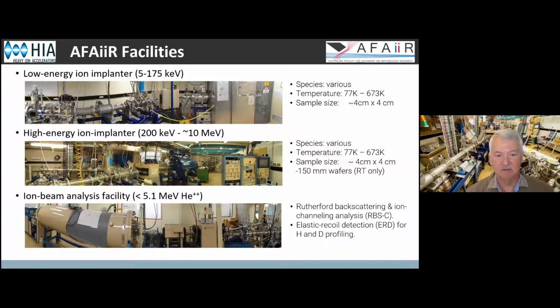This is a tandem accelerator, and I won't go into the details of how the tandem accelerator works, but basically it allows us to get to relatively high energies based on the charge state of the ion. The higher the charge state of the ion, the higher the accelerated velocity for a given potential. So energy range of 200 keV to 10 MeV. Again, similar temperature capability from liquid nitrogen temperatures up to around 450 centigrade. We do have a second beamline on this facility for 6-inch wafer implants, so 150 millimeter capability. That requires some special care to avoid ion neutralization effects in the beamline, and we have that capability with an electrostatic deflector towards the end of the end station to allow us to implant large area wafers without contamination from those neutralized ions. So fairly flexible capability in both cases here.